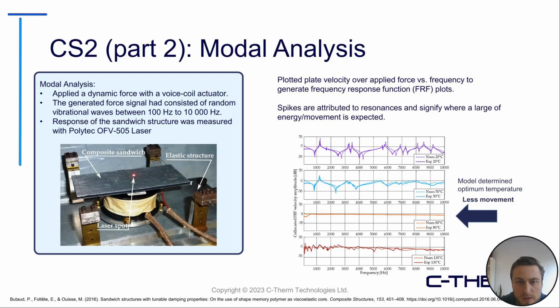Modal analysis is done to measure the response and identify resonances or driving frequencies. So they applied a force with a voice coil actuator. The generated force consisted of random vibrational waves between 100 hertz and 10,000 hertz, which was their operating frequency. The response of the sandwich structure was measured with a Polytech laser. Essentially they created frequency response function plots, taking velocity and dividing it by force, and plotting that against frequency to see where there was a lot of movement and resonances.